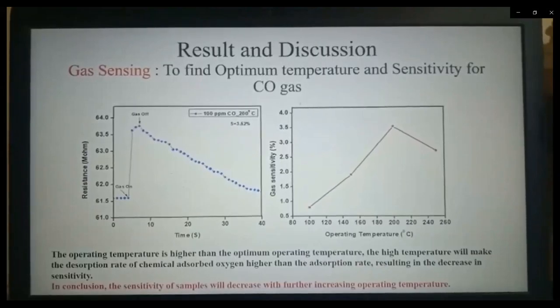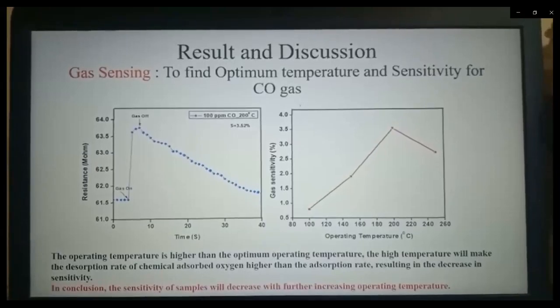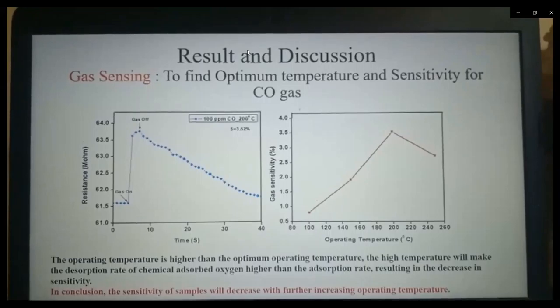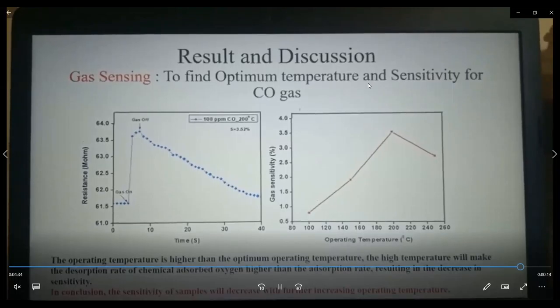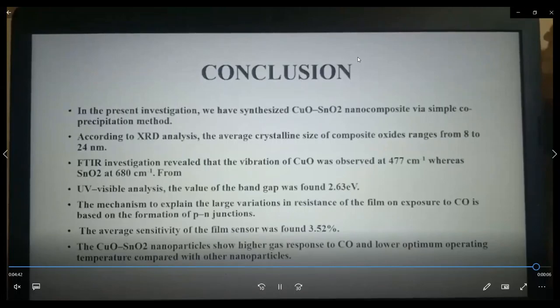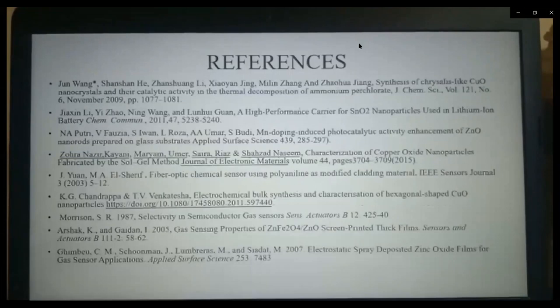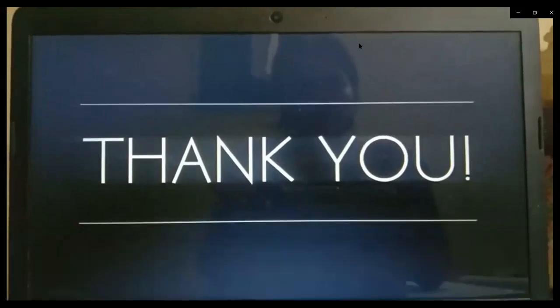Now, whenever we plot a graph of resistance versus time and sensitivity versus operating temperature, we get the highest peak at 200 degrees Celsius for 100 ppm carbon monoxide gas. We calculate the gas sensitivity as 3.52%. The sensitivity of the sample decreases with increasing operating temperature. Whenever we increase the temperature, our sensitivity decreases. This is my conclusion, references, and thank you.